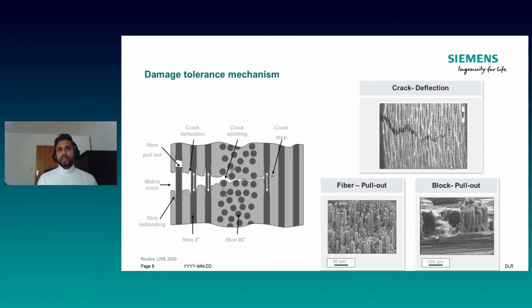Here's a quick view of the damage tolerance mechanism which works behind this material class. If we imagine a crack which initiates within a monolithic ceramic, it goes through the material, and that's why, as soon as your cup falls down, it will break into pieces. But in the case of CMC, we have fibers within the matrix, which means as soon as the crack initiates, it is blocked by the fiber, and instead of going through the material, it goes along the fiber. In this manner, we slow down the crack elongation process, and the damage to the material is then localized.